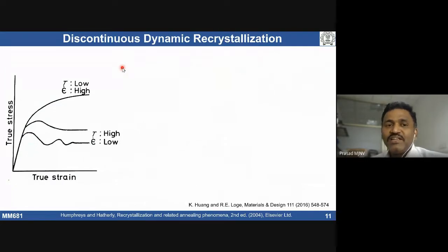It has a characteristic feature in the stress-strain curve. If we talk about CDRX, we simply see a DRV, dynamic recovery kind of curve. But in the case of discontinuous dynamic recrystallization, it is a strain hardening, work hardening kind of thing. When there is discontinuous DRX, we can see a peak followed by a drop in stress, then again a steady stress, or we may also see some serrations in the stress-strain curve, followed by some steady stress.